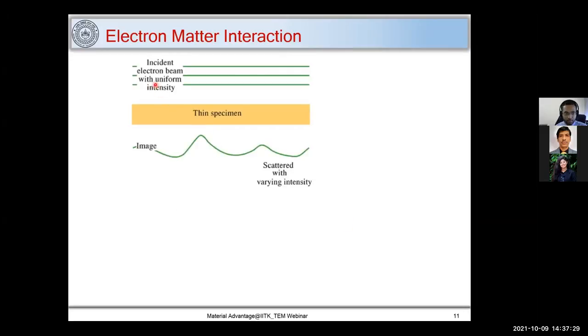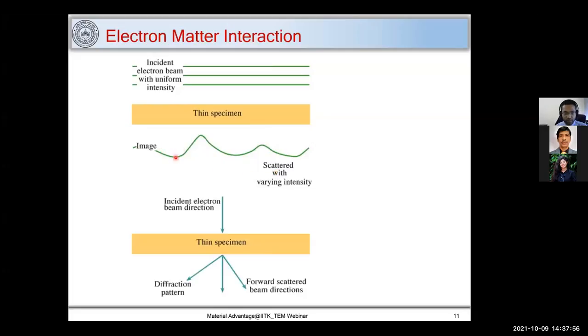Now let's say we have this electron beam falling on your sample, and the sample is very thin. When it interacts with this specimen, there is a change in intensity. Here you have a uniform intensity, but as this beam interacts with the sample, there is a change in the intensity. And this varying intensity creates a contrast, which helps us to form an image in TEM. And why does this intensity vary? Because when this electron beam interacts with this thin specimen, it causes diffraction, with scattering which becomes coherent to each other and thus creates a diffraction pattern. Also, there are some forward scattered electrons. So this incident electron beam has some intensity which gets lost in terms of diffraction and other signals such as elastically and inelastically scattered electrons. So this forms the basis for TEM imaging.